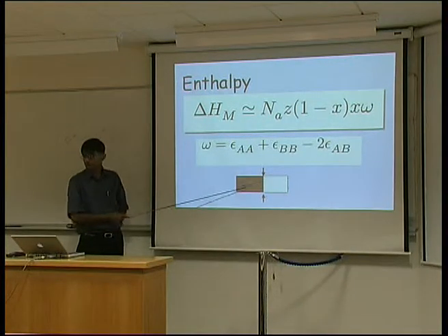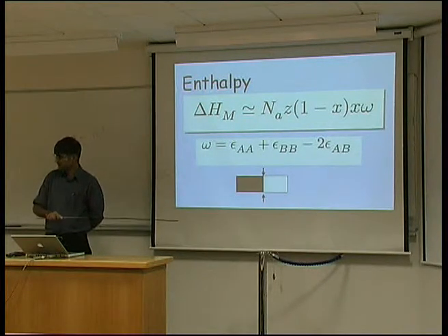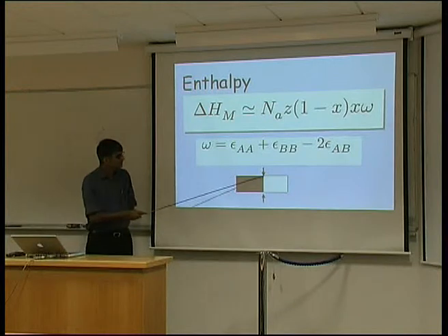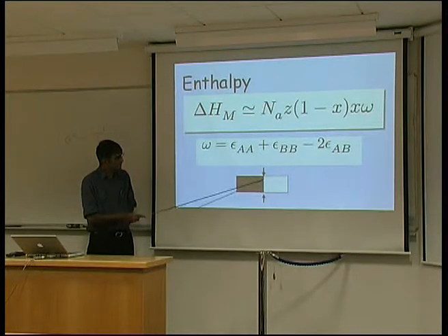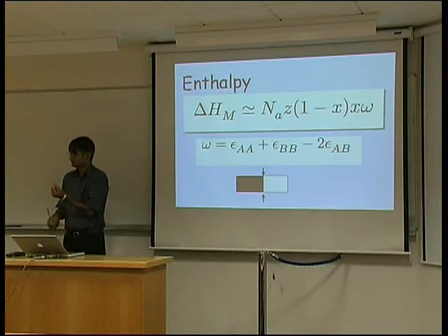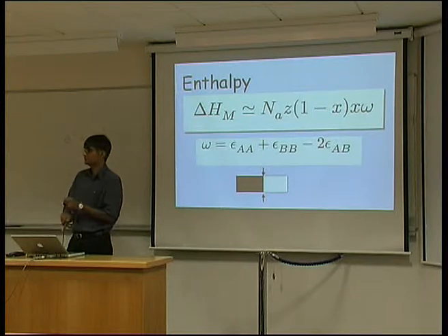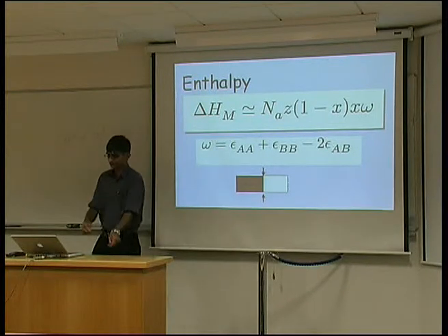I explained to you that when we put large particles in contact with each other, it's only the atoms at the boundary that see each other. So if I scale the enthalpy of mixing with the thickness of that boundary, then that's a chemical interfacial component. So there are two factors. One is structural, one is chemical.